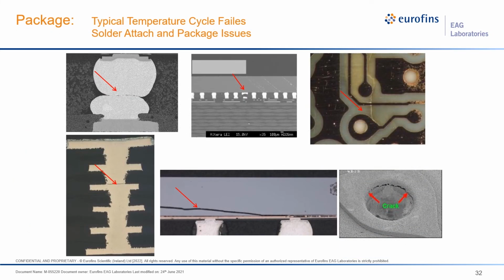On this slide, we're looking at different examples of failures that occurred because of temperature cycling. These failures all show up as cracks in the die, the substrate, solder bumps, bond wires, or the via structures. In the package, different materials will have different thermal expansion coefficients, and as the temperature cycles, the expansion and contraction of these materials will be different from material to material and create a mechanical stress and potentially crack.